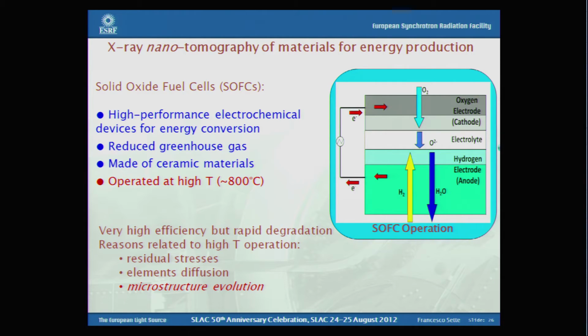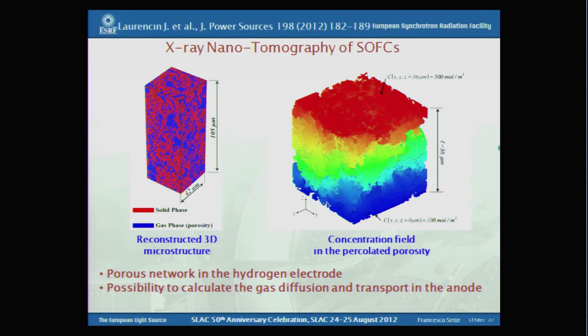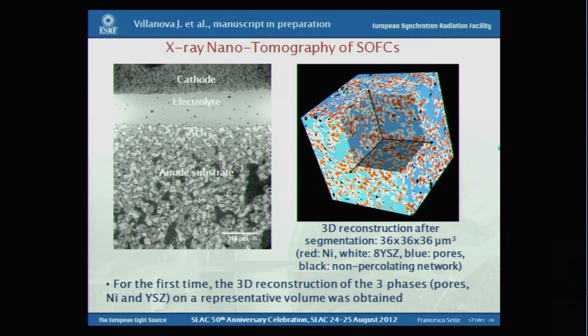So here you clearly see the need for a tool that would allow you to study this kind of effect. And indeed, this is what can be done today. This is a sample out of the tomogram of the order of 100 microns, but the resolution here is of the order of 50 nanometers. So the voxel size is 25. And the kind of information is, for example, this is the anode, that you can fully determine the porous network in the hydrogen electrode, with the possibility to calculate the gas diffusion and the transport in the anode. So these are key elements to understand the properties of the materials and to simulate how you can make it better or make it more efficient.